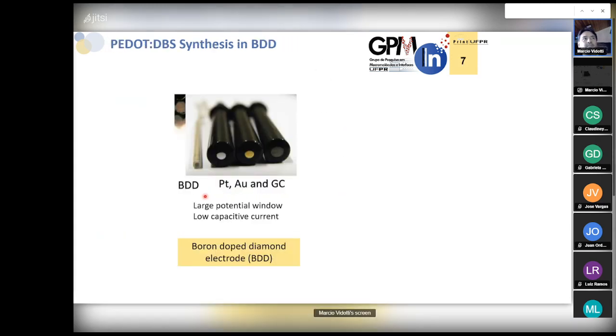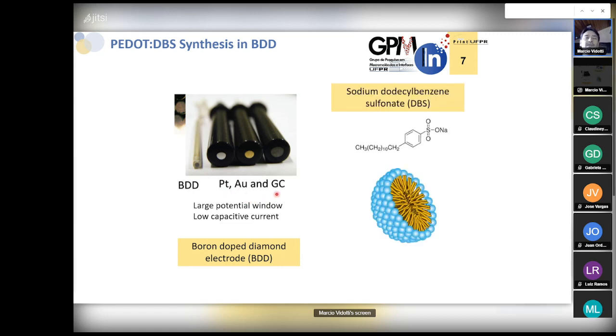So, as I said, we have used these boron-doped diamond electrodes, which are very important for electrochemistry because they have many advantages compared with the common metallic electrodes, such as platinum and gold, and also glassy carbon. And for the second modification, we have chosen to run this project with the electropolymerization of PEDOT, but using surfactants as counter ions. And when you work with surfactants, it's very important that we can also change the concentration above and below the CMC value. So with this, we're trying to find new morphologies of our material.